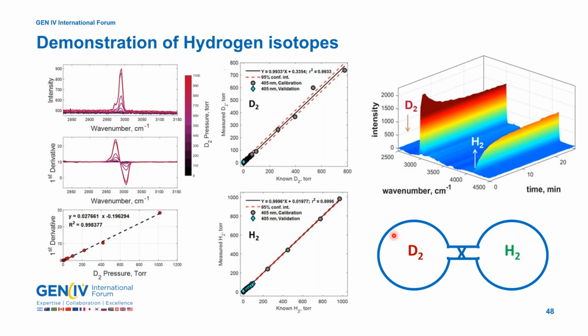And we have our probe located at this chamber, measuring the deuterium concentration in real time. And then we open this valve. When we open that valve in the middle, the hydrogen and deuterium start mixing, and we see a decrease in the deuterium signal with time because we're measuring in this chamber. The deuterium escapes over to the other chamber, and we see an increase in the hydrogen because the hydrogen from the original chamber is now flowing back into this chamber.